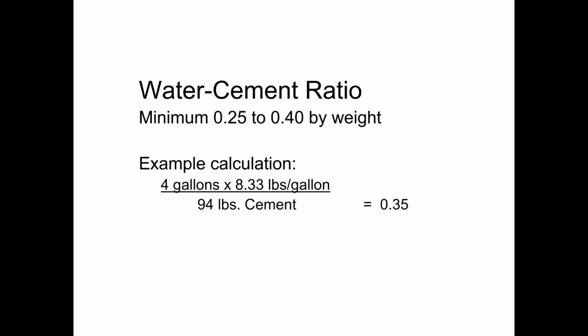Okay, so we have a minimum water cement ratio of 0.25. The water cement ratio can go up from there. For cast in place applications, it's not uncommon to have water cement ratios of 0.5 or even greater, 0.55, 0.6 possibly for some lower strength elements. But typically in precast and pre-stressed concrete, we're working with a higher quality concrete than just a general run-of-the-mill cast in place mix. And so generally you're going to see in precast and pre-stressed operations that the water cement ratio generally maxes out at around 0.40 to 0.45.